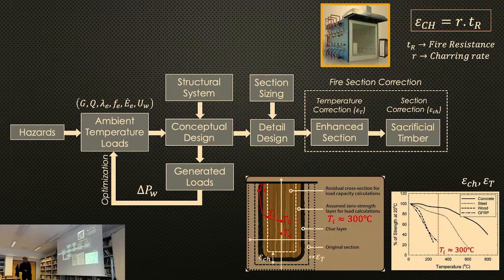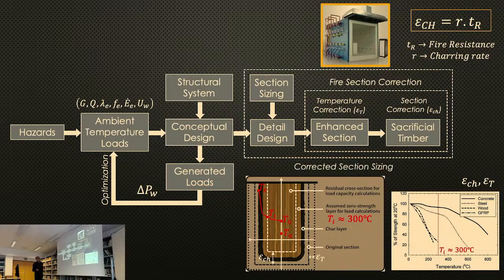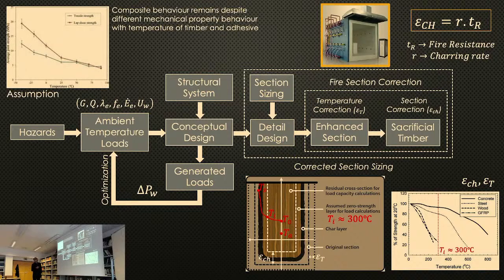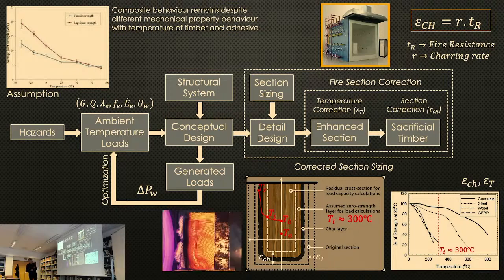So once you get the correction, now you have a correction sizing, then now you have to go and ignore the fact that this is a composite, where part of it is timber, but those timber elements are glued with adhesive. And the temperature of the adhesive and the way its mechanical properties drop, by 90 degrees, the adhesive has no mechanical properties. So they're very different to the loss of mechanical properties for the timber. Nevertheless, I ignore that. So I don't pay any attention to it.